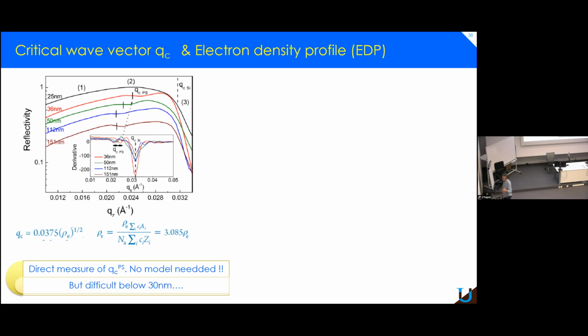Well, this is a more general question. For PMMA, people were using wafers with a silicon dioxide layer, and depending on the tacticity of the PMMA, they were able to generate hydrogen bond interaction between the silanol, the silicon dioxide, and the backbone. That's how they explain this increase in the glass transition. And here we see exactly the contrary.